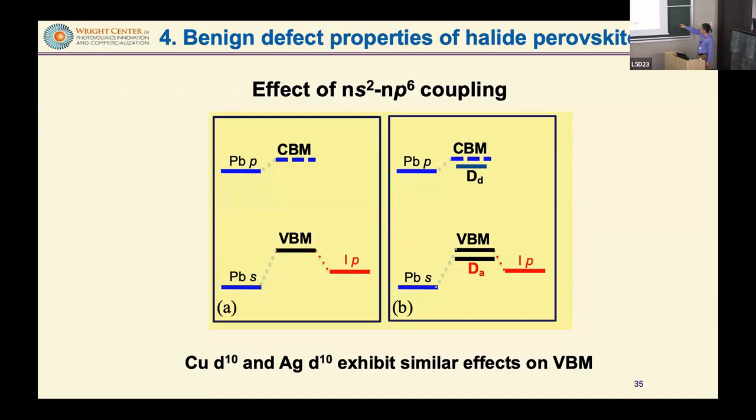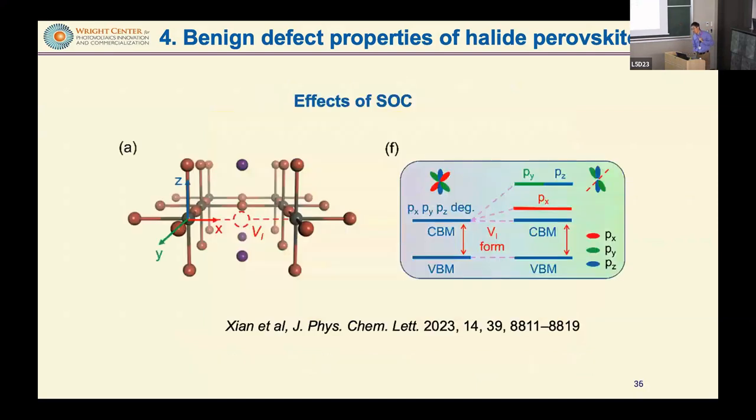And for the electrons, because now we take an iodine away, the environment changes, so that the high symmetry is no longer there, right? If the high symmetry is no longer there, then the spin orbit coupling strength will be reduced. So if that is reduced, then for these dangling orbitals, the orbitals will be higher because the spin orbit coupling is no longer there.